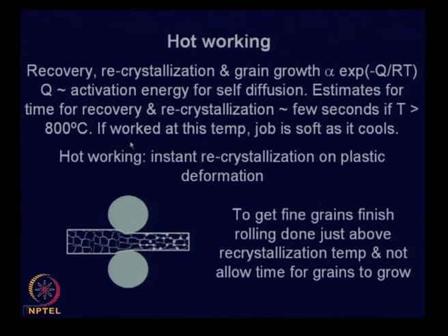So, that means by the time the job cools, if you are working at this temperature, the time it takes for the job to cool to room temperature is enough for recrystallization to take place. So, when the job cools, you will find it is soft. So, hot working is actually instant recrystallization on plastic deformation, which is pictorially shown here. So, if you have this, these are the initial coarse grain structure, and during rolling these grains get elongated, and these are the nucleation sites, and as the temperature is still high, the fresh grains are forming.